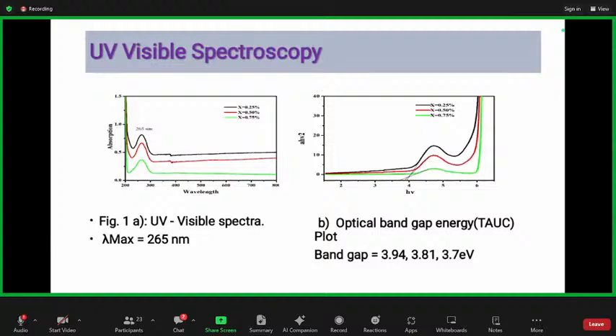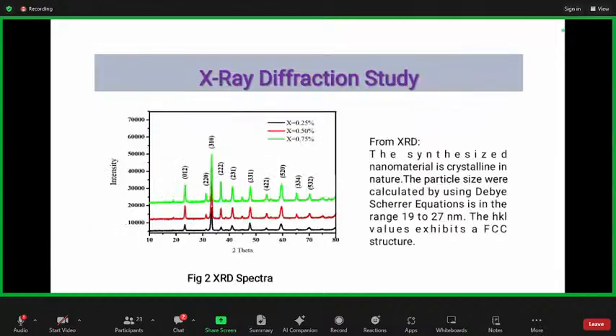Then characterization. First of all, we see UV visible spectroscopy. From this graph on the left side, it has been shown that the lambda max, that is the maximum absorption of these ferrites, is at 265 nanometers, and the optical band gap energy of this material decreases as the concentration of the doping element aluminum increases. Then XRD, that is X-ray diffraction study. From this XRD, it has been observed that the material is crystalline in nature, and the particle size calculated using the Debye-Scherrer equation is found to be 19 to 27 nanometers, and from the HKL values, it shows the FCC structure.